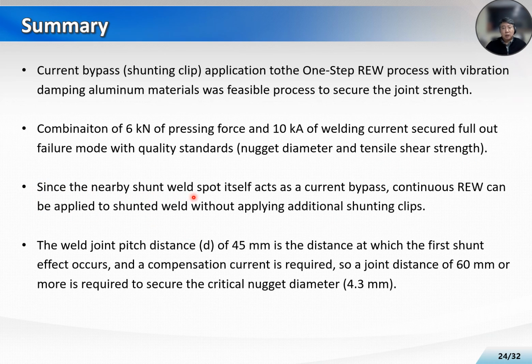Since the nearby shunt weld spot itself acts as a current bypass, continuous resistance element welding can be applied to the shunted weld without applying any additional shunting clips. A weld joint pitch distance, or weld spacing, of 45 millimeter is the distance at which the first shunt effect occurs and compensation current is required. So a joint distance of 60 millimeter or more is required to secure the critical nugget diameter.